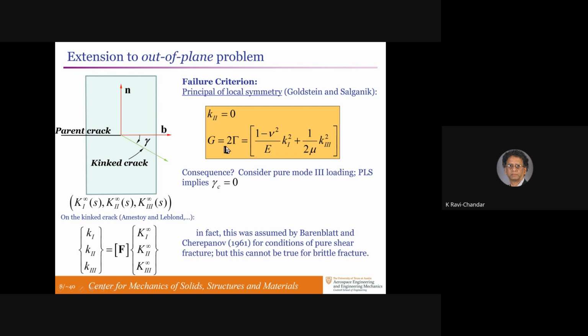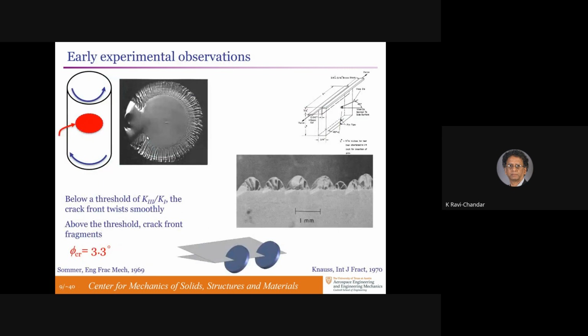But it turns out that if you do this calculation, it says gamma C should be 0, that the crack must grow straight along the B direction. And that's not satisfactory for two reasons. One, it doesn't make intuitive sense that you shear something and it goes along the shear plane when the material is weak in tension. And two, experimental observations contradict it. The crack never grows along gamma equal to 0. In fact, Sommer and Knauss did experiments some 50 years ago.